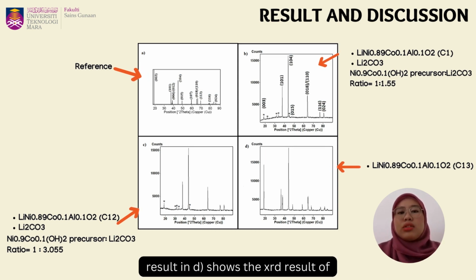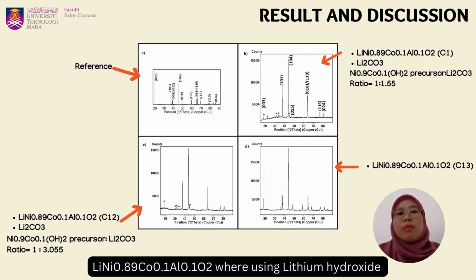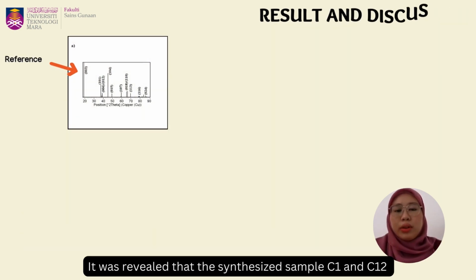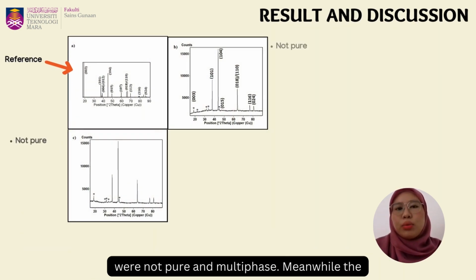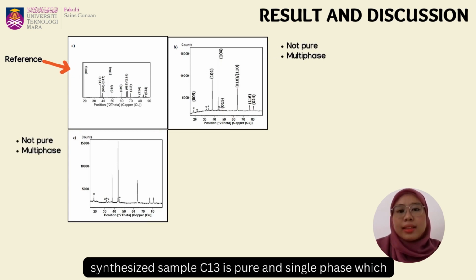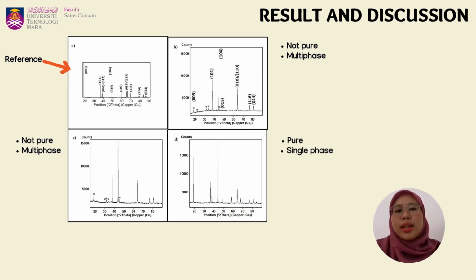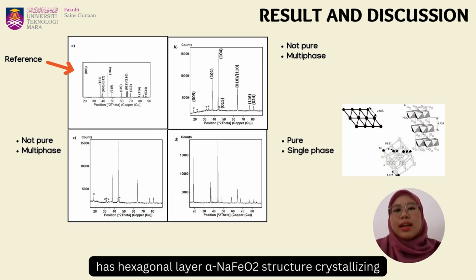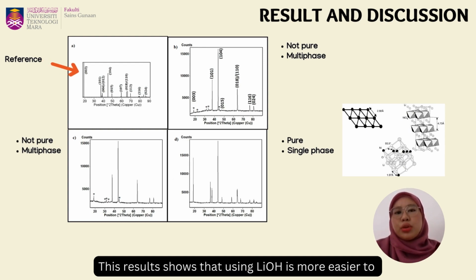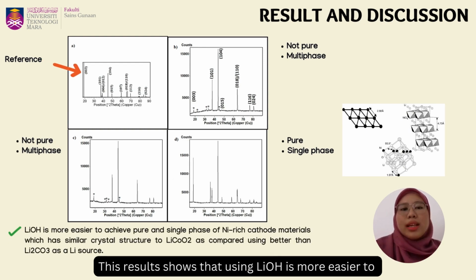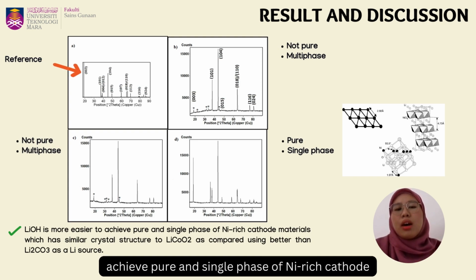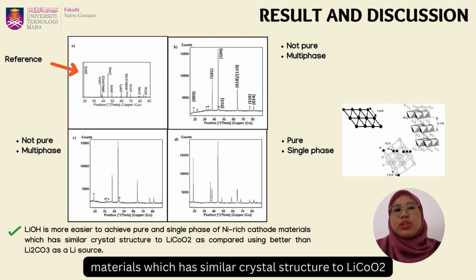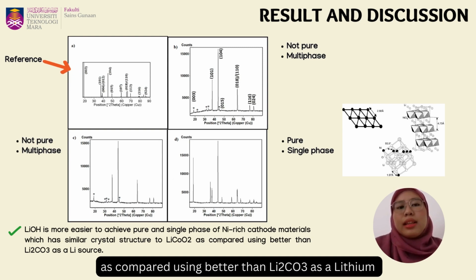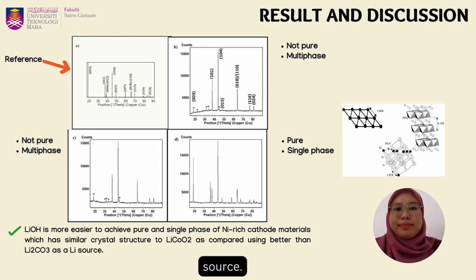The result in D shows the XRD result of nickel-rich lithium nickel cobalt aluminum oxide using lithium hydroxide as a lithium source. It was revealed that the synthesized samples C1 and C12 were not pure and multi-phase. Meanwhile, the synthesized sample C13 is pure and single-phase, which has a hexagonal layered alpha sodium iron oxide structure crystallizing. This result shows that using lithium hydroxide makes it easier to achieve a pure and single phase of nickel-rich cathode materials, which have a similar crystal structure to lithium cobalt oxide, compared to using lithium carbonate as a lithium source.